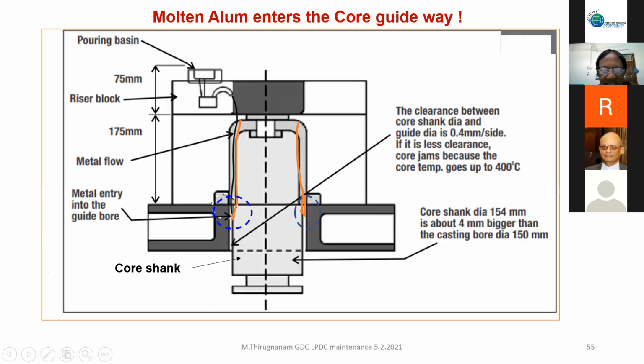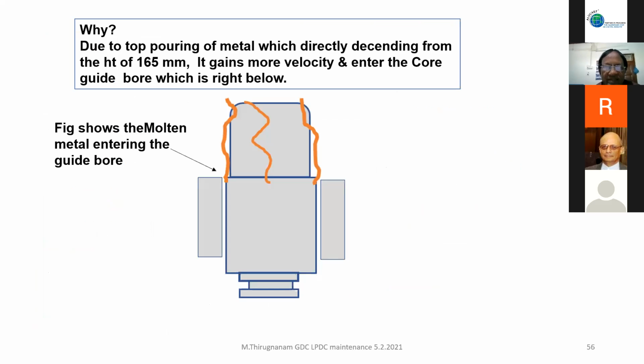See, this is the one I want to show you. Metal enters here and comes straight down into the bore when the gap is 0.4, and the core jams in a day. Again, see this one. When the metal comes from there, the core gate is just right below the metal entry. So 175 plus 50, 225 mm, the metal is coming down. It gains a velocity of more than about 2 meters per second. That's the velocity. It goes and then jams the core.